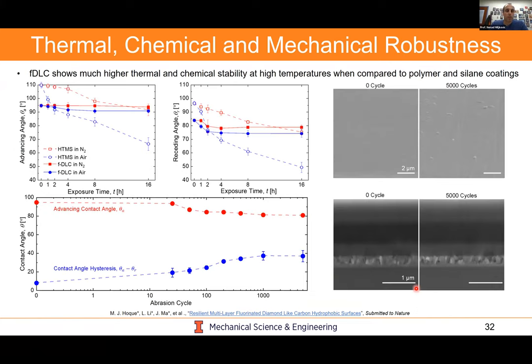Now, in terms of the thermal, chemical, and mechanical robustness, we've done a number of different experiments. What I'm showing in the top left here is the advancing contact angle and the receding contact angle as a function of the exposure time, exposure in a high temperature environment. The dotted lines are for HTMS, which is a conventional self-assembled monolayer, in nitrogen. And the HTMS in air is the dotted blue lines. The FDLC in red is in nitrogen and the FDLC in air. And these temperatures, I believe, were 250 or 300 degrees Celsius of exposure. And you can see that the FDLC maintained its performance over time, whereas you get significant degradation of this HTMS formulation. Same for the receding angle here on the right.